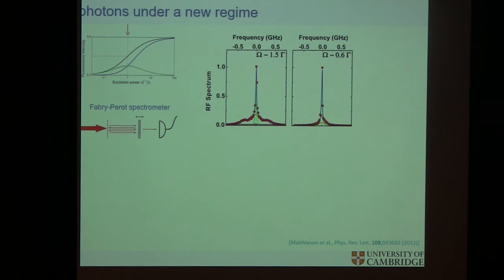And then if you tune below saturation, or right around saturation, now you get this sharp feature, and then you get a single Lorentzian underneath, not as strong, but still finite. And if you go further, even that component disappears. You're left with a very sharp feature, which corresponds to the elastic scattering component. So even the spectrum of light coming from a two-level system looks just like a laser in the weak, or relatively weak, excitation. Now, this is where, usually, there are three groups in the audience. One group is from solid-state spectroscopy that says, what? What do you mean two different types of emission? The other group is atomic people and they say, yeah, of course, but that's classical. And then there are the people in between who know everything about this, who figured out that these are neither classical nor, what are you talking about.